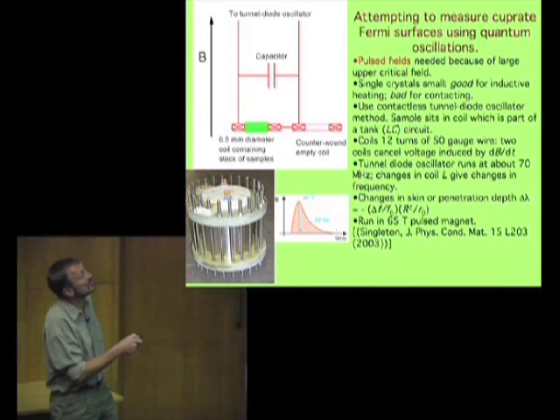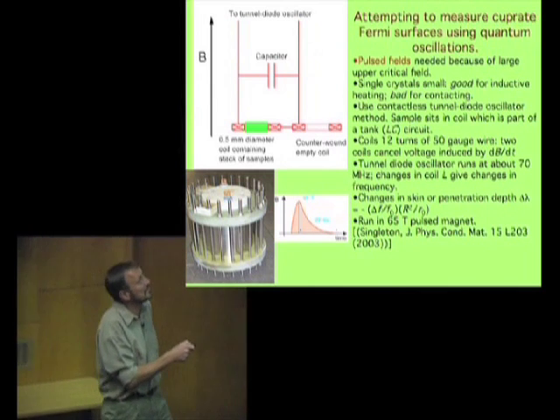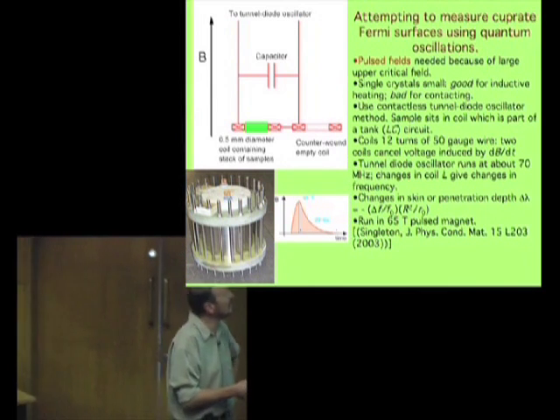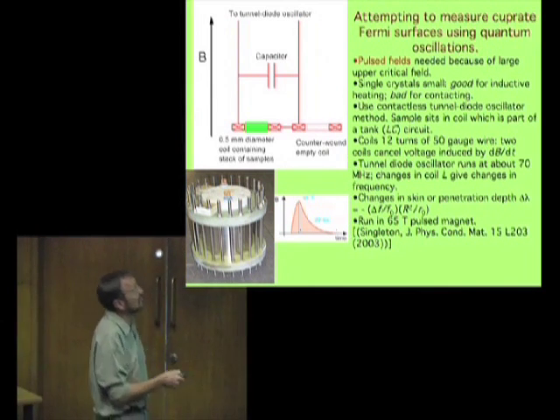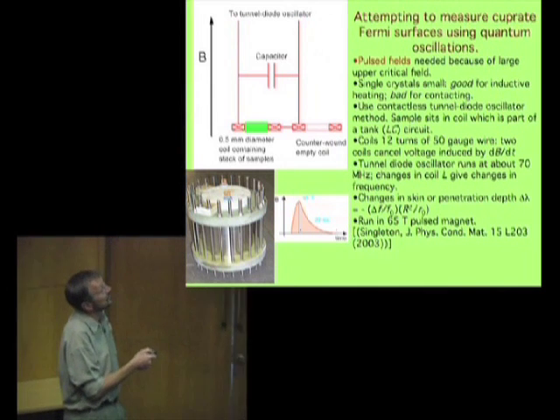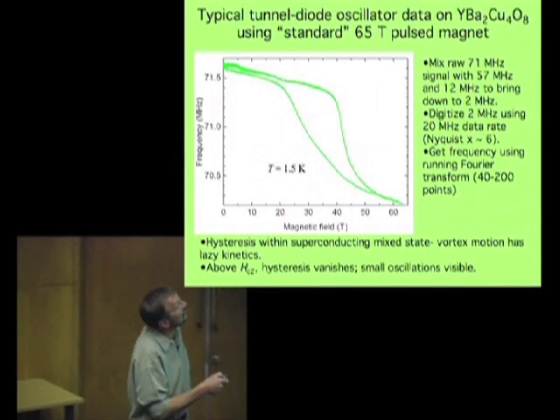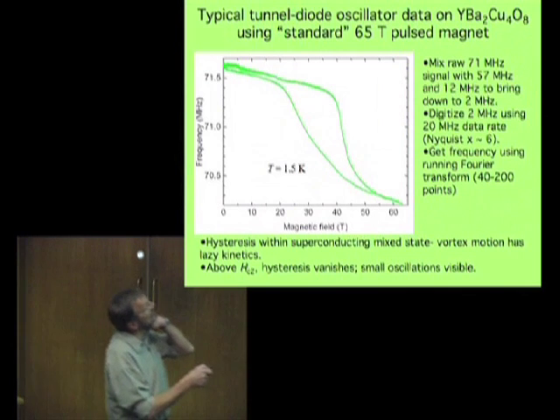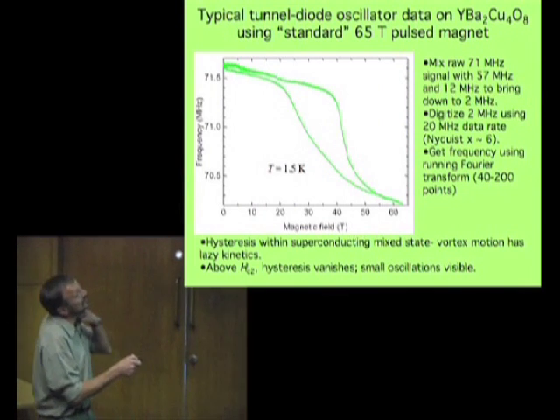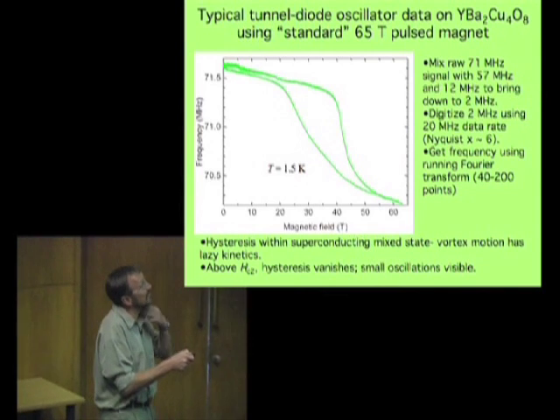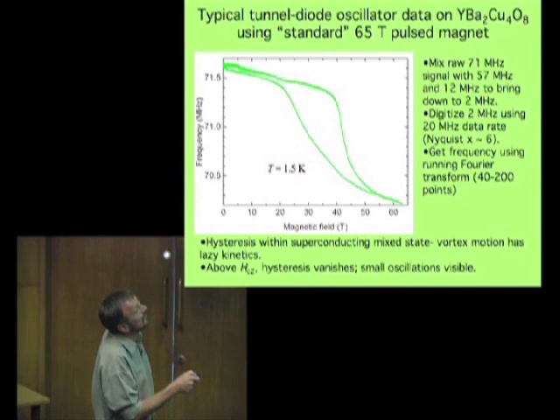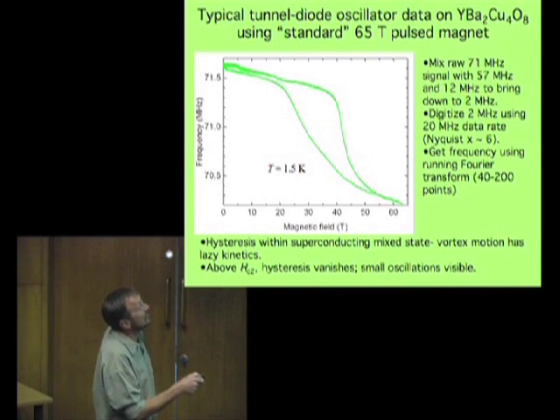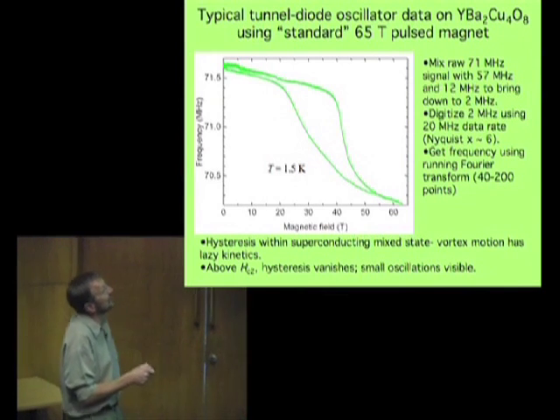Anyway, any changes in conductivity of the sample are going to be manifested as changes in frequency of the circuit, and we can collect data fast enough so that we can do it all in a pulse magnetic field. So here's the very first measurement of a cuprate done in a pulse magnetic field with evidence for quantum oscillations. It's something I did about a year ago on yttrium barium 2 copper 4 oxygen 8, the so-called 1248 compound.